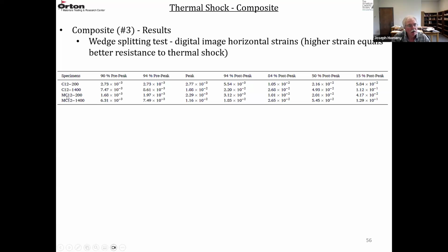So these are the samples, C12 and MC12 at the two different curing temperatures, 200 and 1400 degrees C. This is at 90% of the pre-peak load, 94% of pre-peak, at the peak, 94% post-peak, 84% post-peak, 50% post-peak, and then 15%. So if you start looking at these numbers, these are the strains. This is 1.29 times 10 to the minus 1. This is 1.12 times 10 to the minus 1. So these are pretty large strains post-peak on the samples cured at 1400 degrees C. The strain is a little bigger in the finer material.